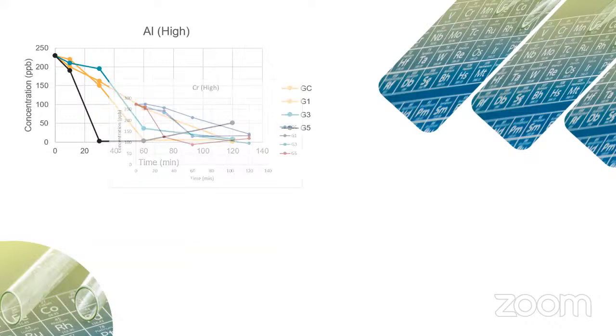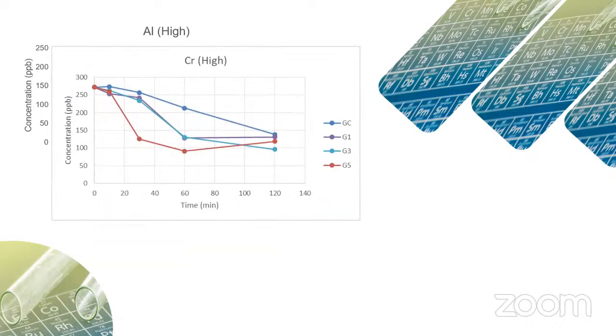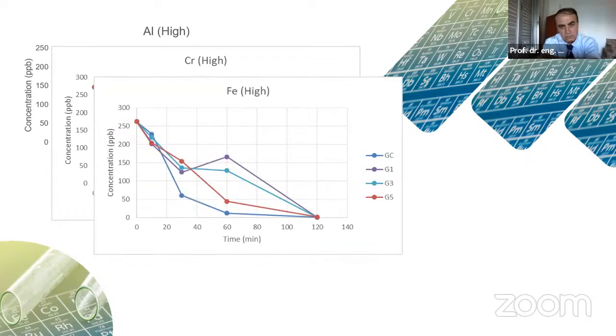metals. Now we can see sometimes we have absorption-desorption. Sometimes it drops and increases, but this was only with low percentages. With high percentages of titanium, we can see full absorption of heavy metals and complete removal at 120 minutes.